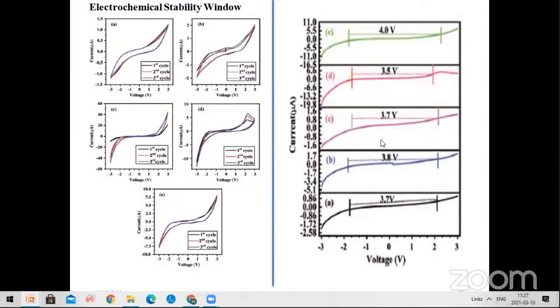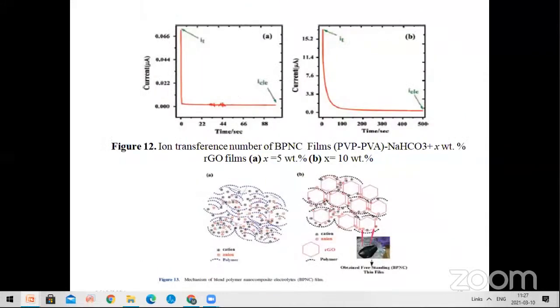As we increase the concentrations, the stability of the electrolytes is enhanced. So it means that it is feasible for use in energy storage applications. And this is the broad mechanism of the energy storage applications, and we can check the ion transfer for the samples of 5 weight percent and 10 weight percent. The ion transfer number is 0.98, which is suitable for the energy storage device.